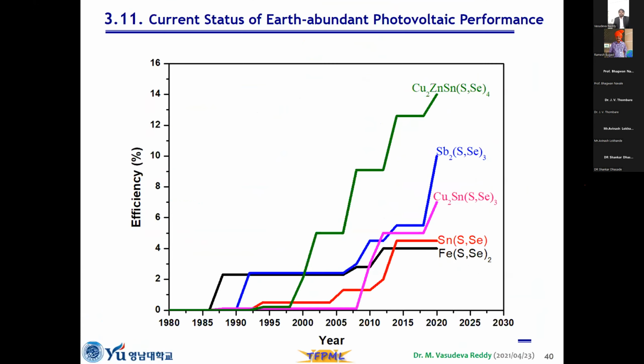So this is the current status of the earth-abundant, low-cost material solar cells. If you see here, CZTS is showing around 15%, and currently antimony sulfoselenide is showing around 10%, and tin sulfoselenide is showing around 5% efficiency. Still, as I mentioned, there is one disadvantage with the quaternary and other processes. There are a number of materials, so controlling the phase and other things is critical. So we can go for ternaries like tin sulfoselenide, antimony sulfoselenide and iron sulfoselenide. These are promising, low-cost materials.